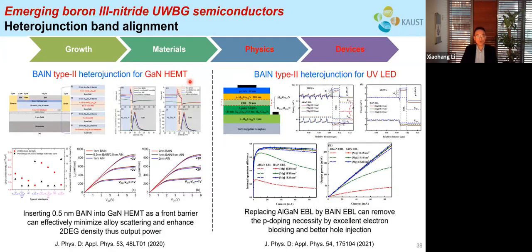When we reported our results, it was noticed by the experts in the field. Compound Semiconductor, a leading technical media in our field, highlighted our results as the title of the newsletter they send all around the world. The title was "Researchers Discover Unique Boron Aluminum Nitride Properties." We have also taken advantage of the type 2 heterojunction band alignment for gallium nitride high power and high speed devices, as well as UV LEDs. In both scenarios, we noticed a considerable improvement in device performance by having the type 2 heterojunctions.